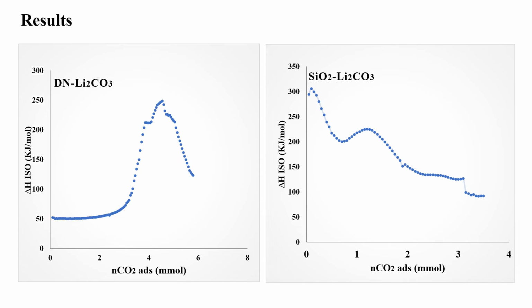The isosteric heat results are determined using the Clausius-Clapeyron equation, which shows differences between our sorbents. Starting with diatomite-based adsorbents, the isosteric energy increases with the CO2 adsorbed amount from 50 kJ per mole to 250 kJ per mole at 4.5 millimole of CO2. This evolution reflects the easiness of adsorption initially, occurring over the low-strength sites, followed by chemisorption beyond 3 millimole of CO2.